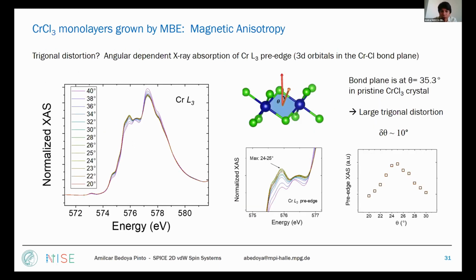The second point was the trigonal distortion. Trigonal distortion is usually difficult to measure, but in this PRL paper, they treat it as an angle. This is the bond plane in which chromium and chlorine are bonded, and it lies at 35.3 degrees in the theoretically relaxed structure. If you do angular-dependent measurements, in our case we are able to see an offset of this bond plane with respect to the angle.